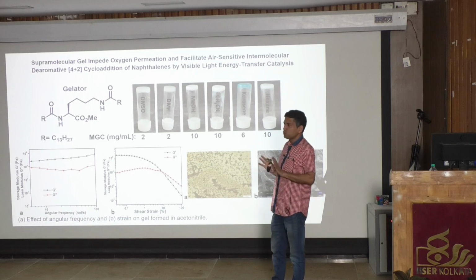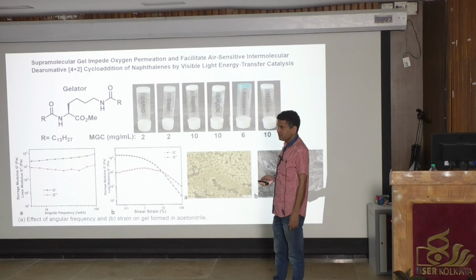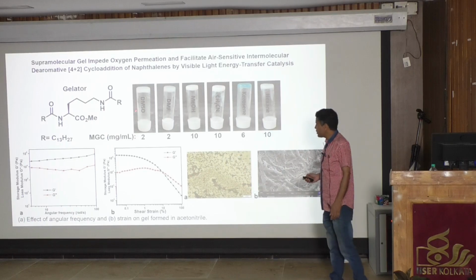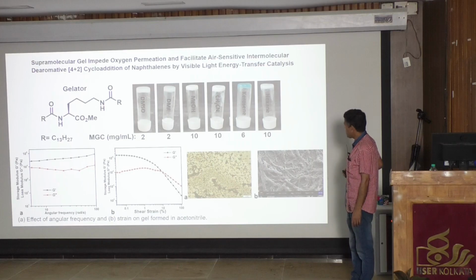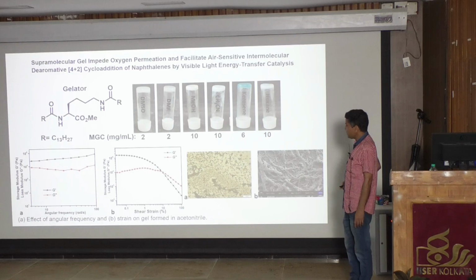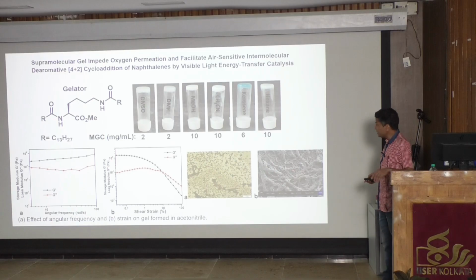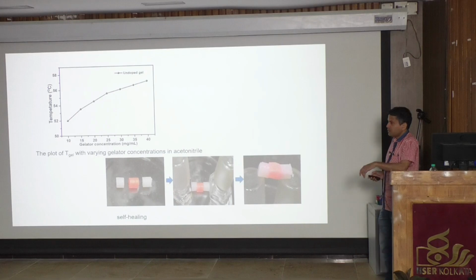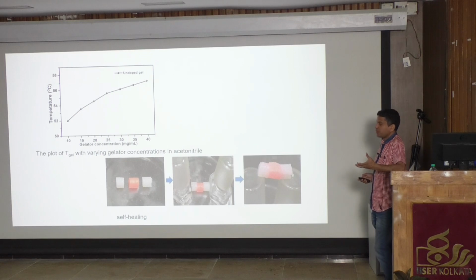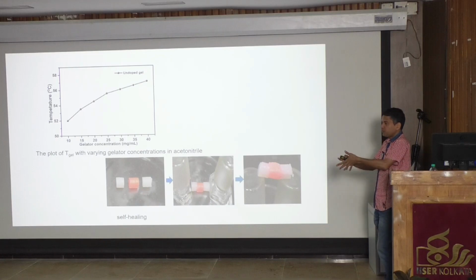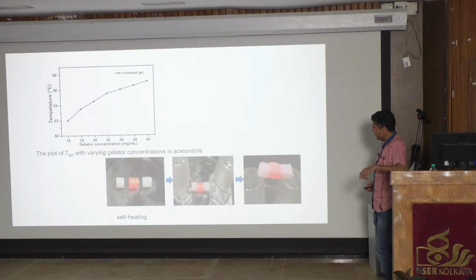Now the gel has no aromatic ring, nothing to absorb light. With our gelator, we make gel; it forms gel in DMSO, DMA, methanol, acetonitrile, kerosene, hexane, and we started with the rheology. The gel is forming fantastically, and from the morphology, it is fibrous in nature. Also, we have studied the melting point of the gel, and we have seen that with increasing gelator concentration, if the gel is very concentrated, the melting point increases. And the gel has very good self-healing property. That means if we cut the gel into pieces and put them together again, they will self-heal and make a single bar or single fiber from the gel.